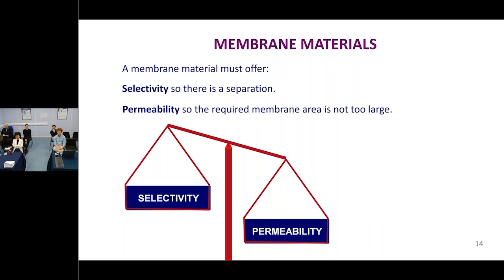a membrane. In the simplest case, we can think in terms of the flux, which is the amount per unit area per unit time. But that, of course, will depend on the driving force. And so when we want to compare membranes, we often actually normalize that with respect to the driving force. If it's a gas separation, that's an effective pressure difference, to get something that we'll call permeance. But that in turn will depend, if it's a simple film, on the thickness of that film. If it gets thicker, less stuff goes through.